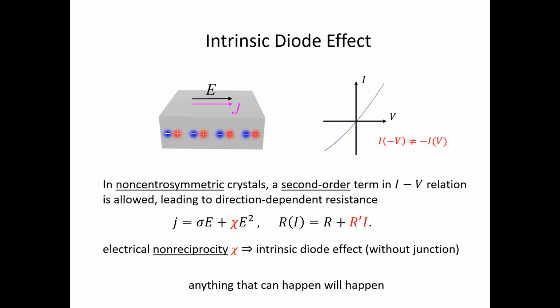For example, consider as a simple example a compound conductor made of two different types of atoms arranged in this way. Basically, you can think of the system as an array of small electric dipoles. In such a conducting crystal, there is no macroscopic electric field, but still inversion symmetry is absent. So this makes you wonder, according to the teaching of Landau, we should think in terms of symmetry. If the crystal structure breaks inversion symmetry, there could in principle be a correction to Ohm's law.